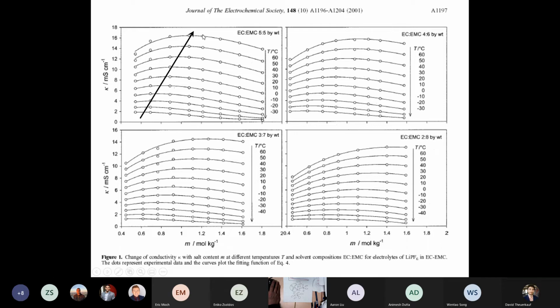And what I wanted to show you in this chart is a couple of things. First of all, the conductivity increases with temperature. That's obvious. But next, if you look at the maximum in the conductivity as a function of molality, the concentration at which the maximum conductivity occurs shifts with temperature. So you might say, oh, I want to make the highest conductivity solution of EC/EMC 5 to 5, and you're operating your cell at 20 degrees C, so you pick 0.9 molal. But then you realize when you discharge cells or charge cells fast, they have internal heating, and their temperature would be more like 50, and you say, I should have made a different concentration electrolyte. So it's just good to know that electrolytes behave like this.